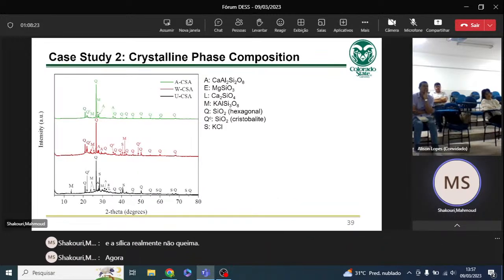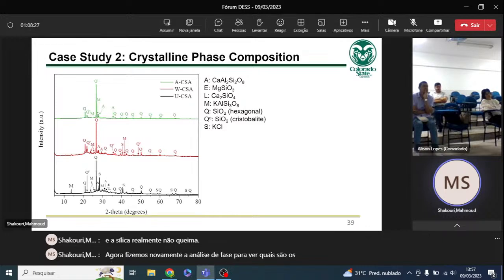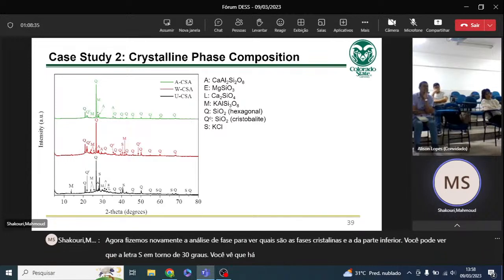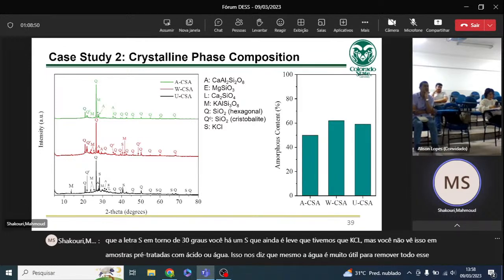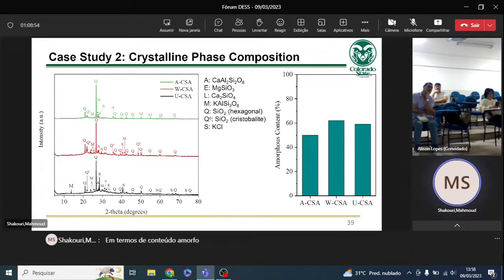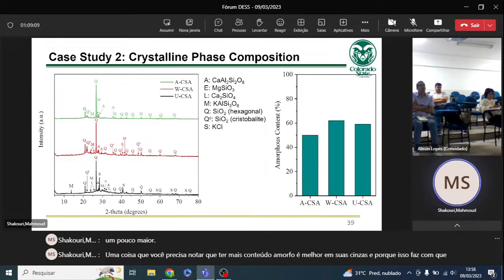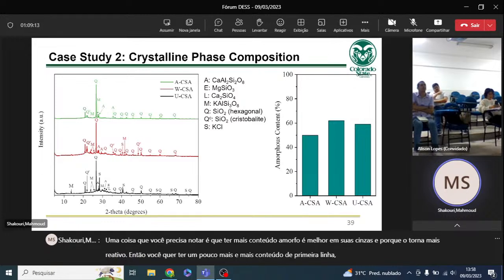Now, we did, again, phase analysis to see what the crystalline phases are. The one at the bottom, you can see the letter S around 30 degrees, that's sylvite, KCl, but you don't see that in acid or water pre-treated samples. That tells us that even water is very useful for removing all of those alkali contents in your ashes. In terms of amorphous content, they were all very similar, with water pre-treated being a little bit higher. One thing you need to notice is that having more amorphous content is better in your ash because it makes it more reactive. So you want a little bit more amorphous content, but about 45%, 50% is a very good number for these types of ashes.